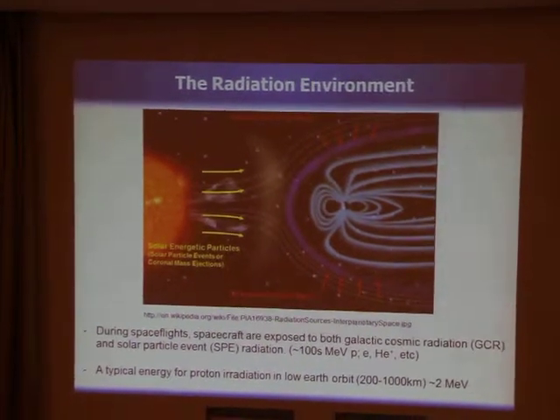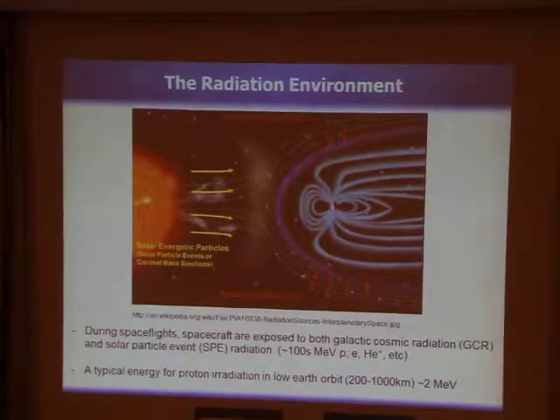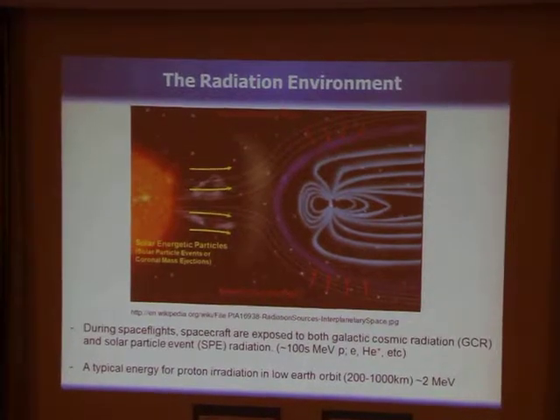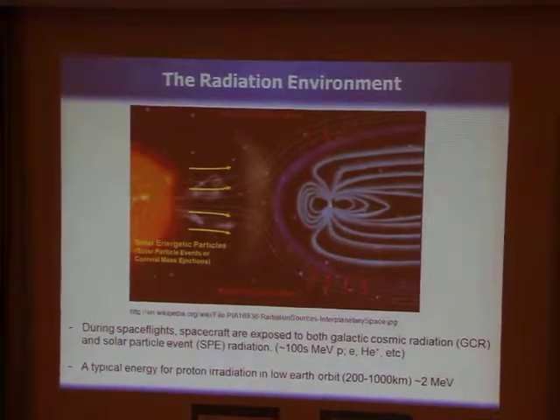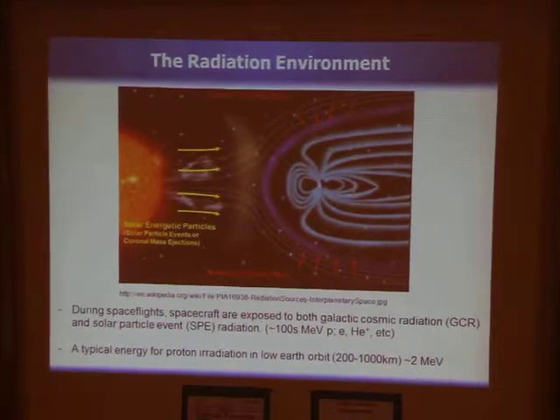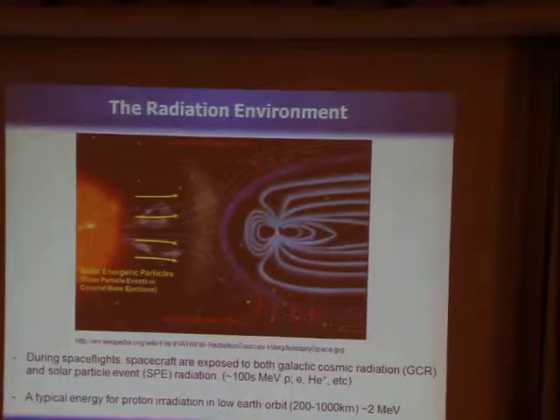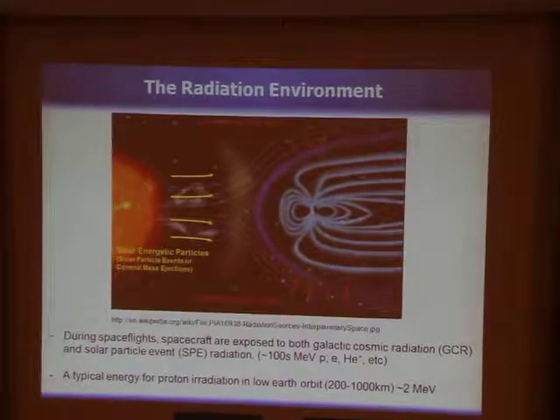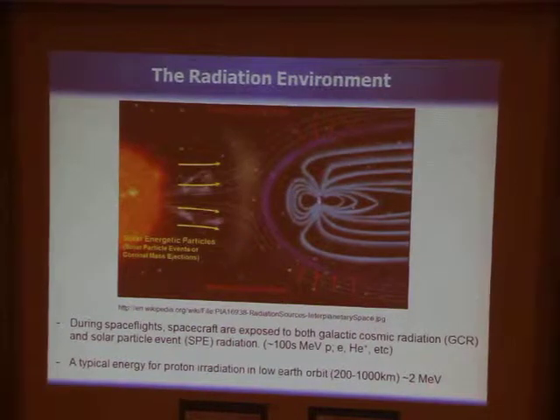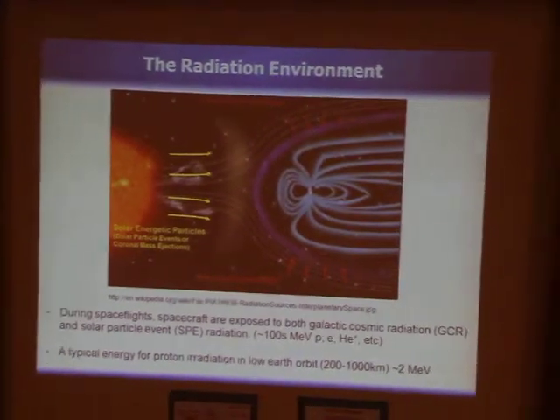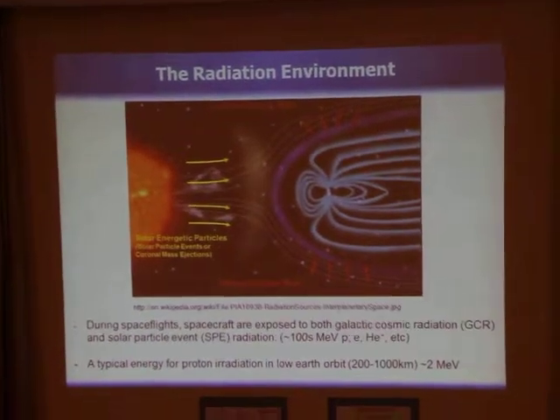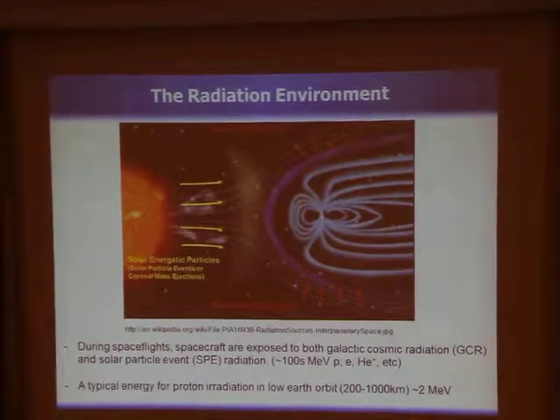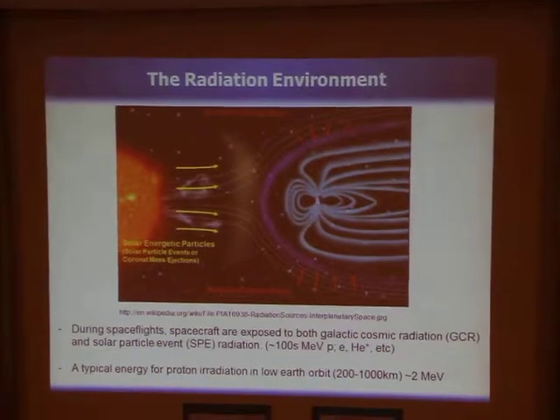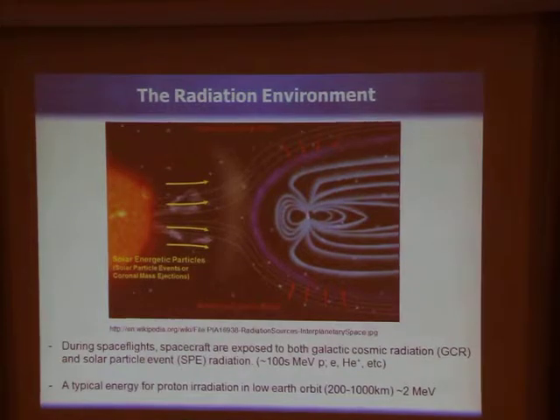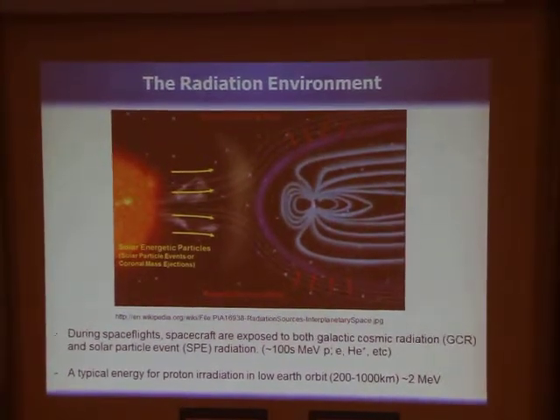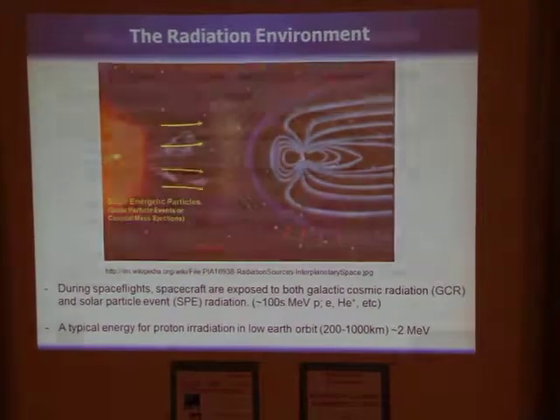However, the magnetic field of Earth protects us from these highly energetic particles, as well as the atmosphere. However, when spacecraft operate at so-called low Earth orbit, which is at 200 to 1,000 kilometers above the Earth, there is very high density and dose of irradiation. Mostly those are protons of 2 to 7 MeV and higher energy. So polymer nanocomposites are obviously very appealing structural elements for applications in spacecraft due to their lightweight and strength. However, they are susceptible to irradiation damage, and it is necessary to develop more radiation-resistant polymer composites.